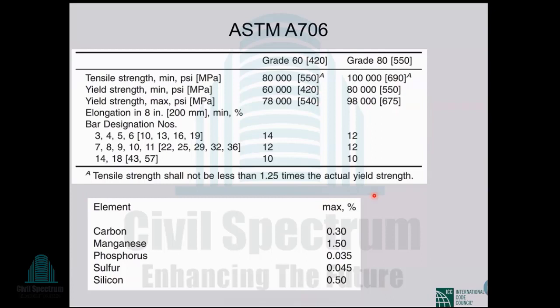In ASTM A615, only phosphorus is defined, that phosphorus cannot be more than 0.06%, and maybe another one is defined, but these are not defined in the ASTM A615. But in ASTM A706, the metallurgical composition is clearly defined. And tensile strength shall not be less than 1.25 times the actual yield strength. So it means that if a rebar is according to ASTM A706, that means it is of ductility class D. So that's why, without checking, if steel is produced according to A706, without any further condition, we can use that.